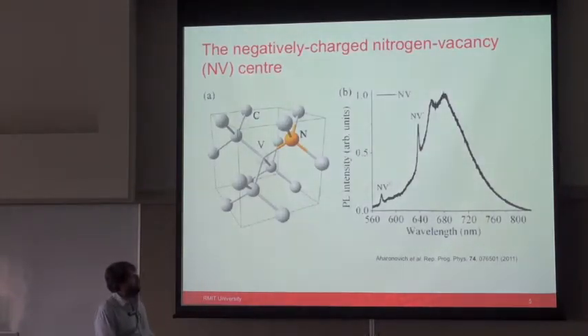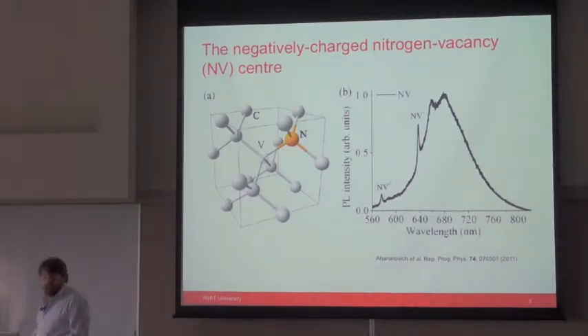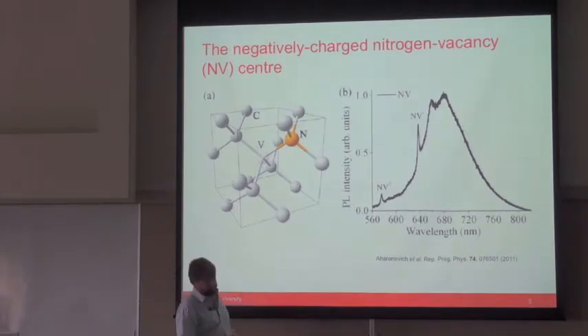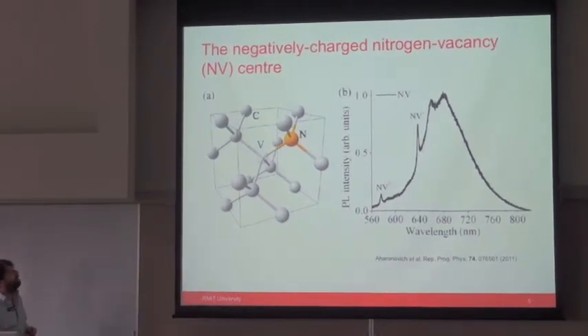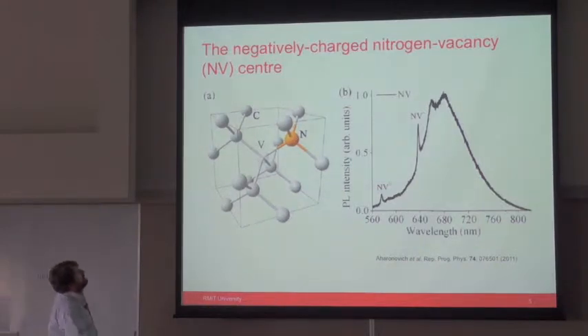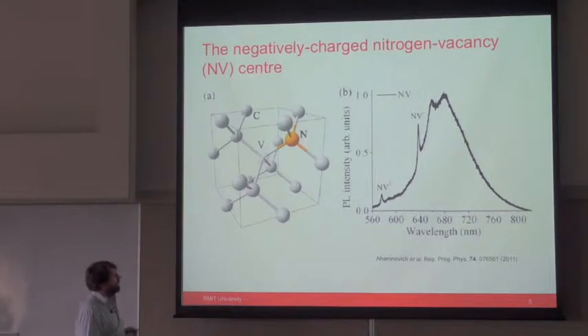For many people, the interest in diamond begins and ends with this beast, the nitrogen vacancy color center. The nitrogen vacancy color center is a really remarkable defect in diamond. It's formed by a substitutional nitrogen being next to a vacancy, so a lack of a carbon atom. And nitrogen is a fairly common impurity in diamond. It incorporates well into the diamond lattice, and so it's relatively easy to make things. The nitrogen vacancy center is thermodynamically more stable than either a nitrogen or a vacancy alone.